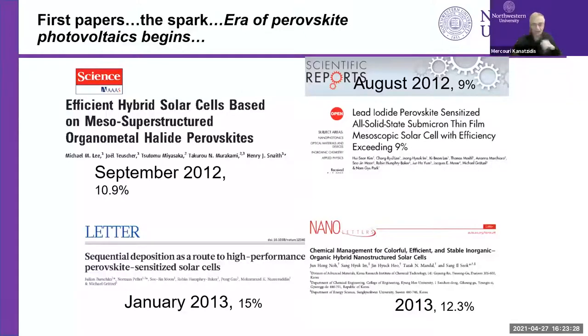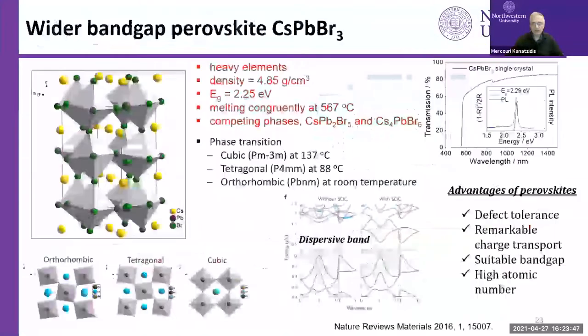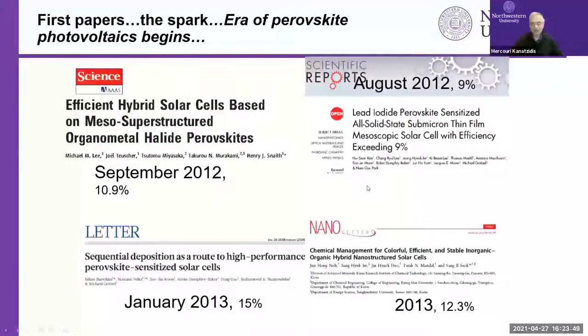And that really started the revolution in the field of perovskite photovoltaics, which to this day has resulted in efficiencies of over 26%, which is remarkable and is higher than any other material, including silicon. So why was this material so good? It's because they had very long lifetimes, despite the fact that they were not really that perfect and not really that pure. In other words, they were defect tolerant.